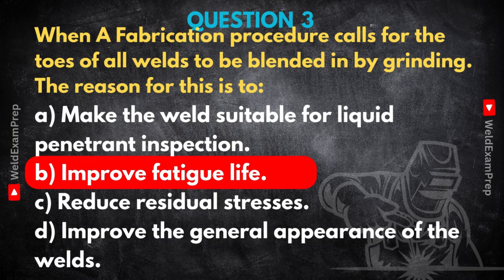Think about the toes of a weld. They are, by nature, geometric discontinuities. You've got this sharp, abrupt change in shape where the weld metal meets the parent material. These sharp transitions create what we call stress concentration points, stress risers. Think of it like a tiny notch cut into something. Where's it going to break first? Right at the notch. So when a component is under cyclic loading, repeated stress, vibration, like in bridges, aircraft, machinery, those stress concentration points are prime spots for tiny cracks to start. And once a crack starts, under continued cycles it grows and grows until eventually fatigue failure.